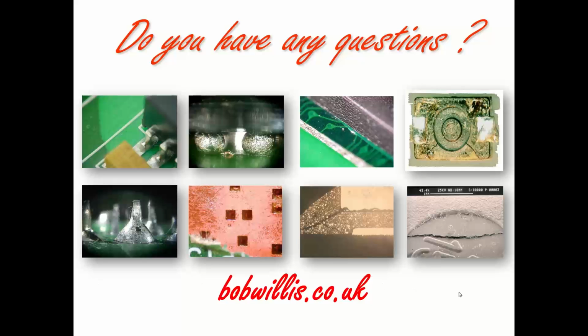The first question I've had is, do all components suffer from potential damage from the inclusion of moisture? Well, obviously, well, I say obviously, perhaps I shouldn't say that, but resistors, capacitors, no. LEDs, yes. Light emitting diodes can suffer. In the early days, the suppliers of LEDs were demonstrating that some of the smaller, simpler, cheaper parts would suffer, and I was never able to create it myself. I wasn't able to generate, and you know how I love making videos to show defects happening. I wasn't able to do that.